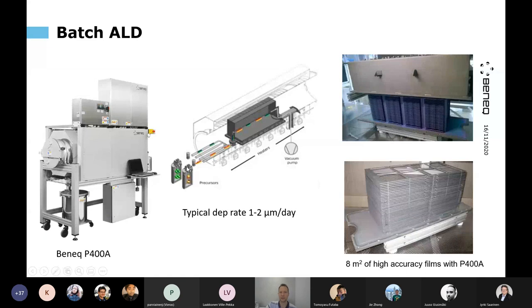And when making an optical stack, then we just have more of these precursor sources. And instead of pulsing this A and B, we start pulsing, let's say, A and C to deposit another material. Typical deposition rate is 1 or 2 microns per day, depending on the setup, temperature, materials, and other things, but roughly, a rule of thumb, 1 or 2 microns per day.